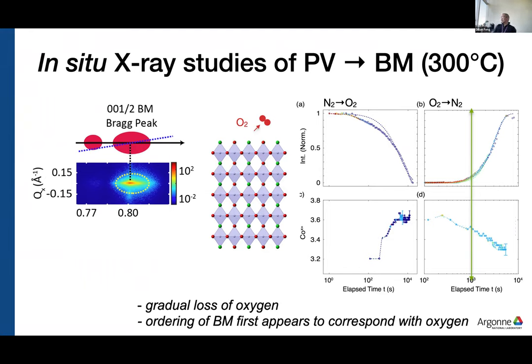And so we do see, instead of the relatively rapid change in the oxygen concentration, this slow change in the oxygen. It's a gradual loss of oxygen. And because we're looking at both the Bragg peak intensity going up as well as the XANES, you can see that the ordering of the Brownmillerite peak first happens before you get a lot of oxygen.